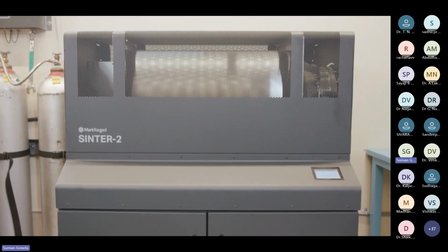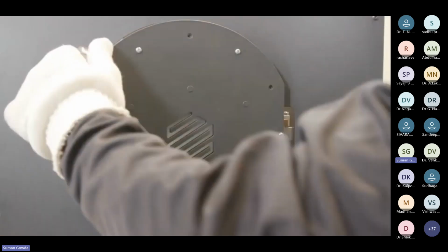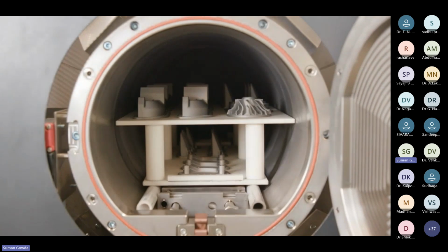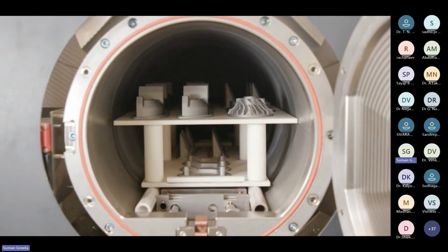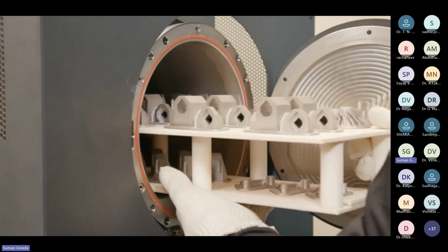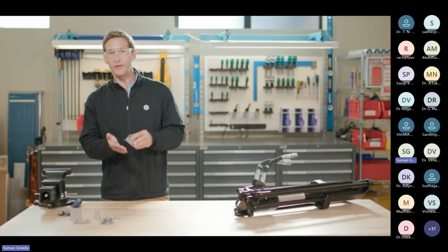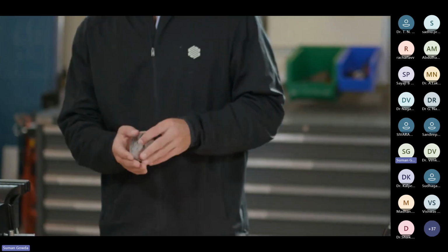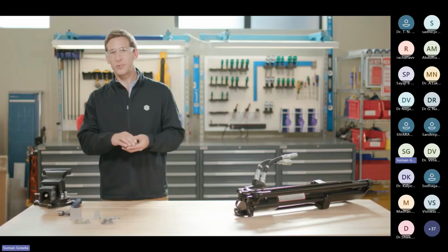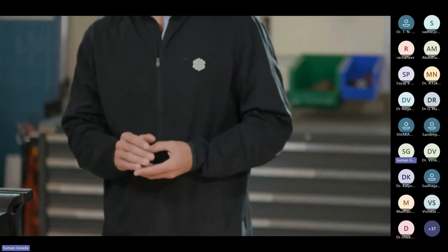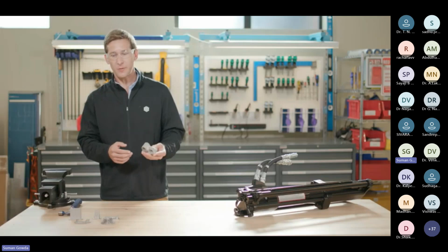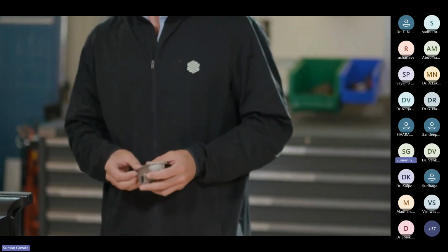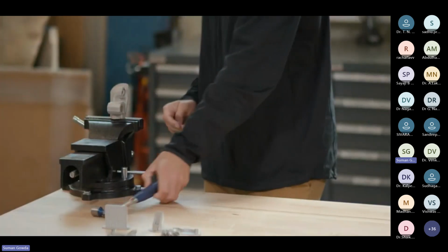Markforged sintering furnaces use a carbon-free retort to ensure part quality and alloy composition standards are met for our finished pieces. Each run takes about a day and can be monitored remotely using the Eiger software. Once a run is complete, the setter tray full of finished metal pieces can be removed from the furnace. Once removed from the raft, these parts are ready for use. In the furnace, the layer of printed release material between supports and the raft and your printed part remains powderized. This allows the structure to be tacked to the raft to better control shrink and accuracy throughout the process, but also an easy release after sintering.